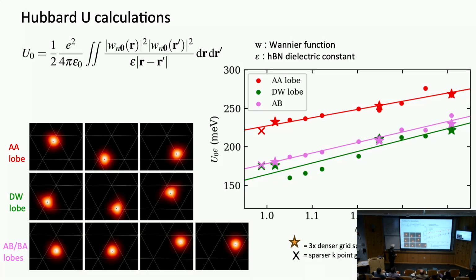So you need these 10 different localized orbitals on the Moiré scale, produced by the same methodology now, but for a much larger lattice. And with these localized orbitals, you can calculate these quantities, like the on-site interaction, on-site repulsion of electrons, effective electrons on these orbitals, as well as the hopping matrix elements that I was telling you, which are the ingredients of the more complicated Hubbard-type model that I was trying to hand-wavingly describe.